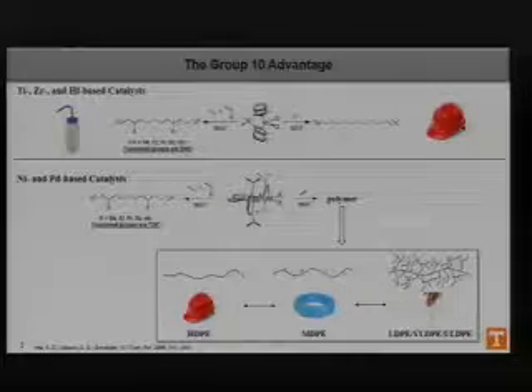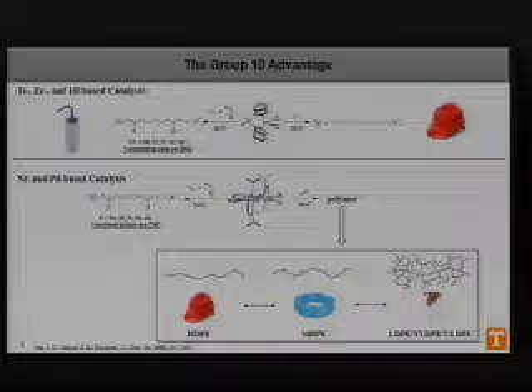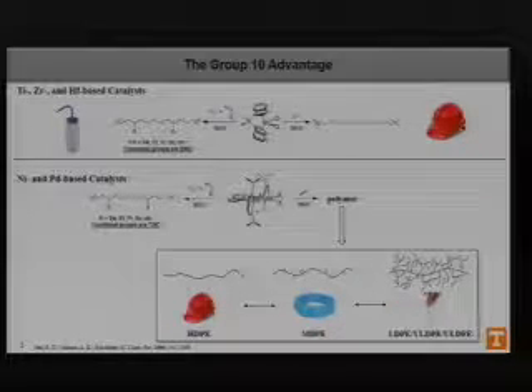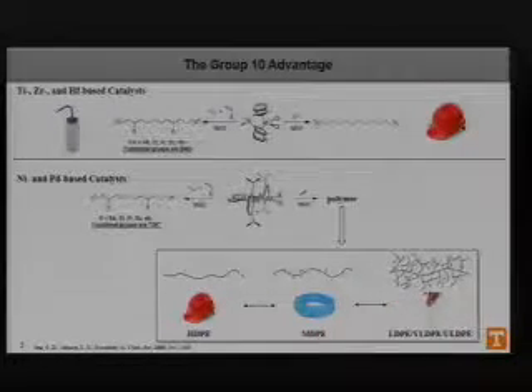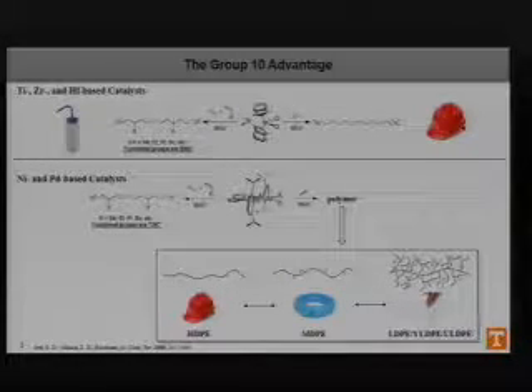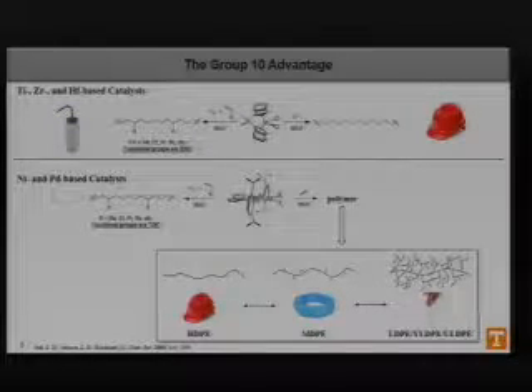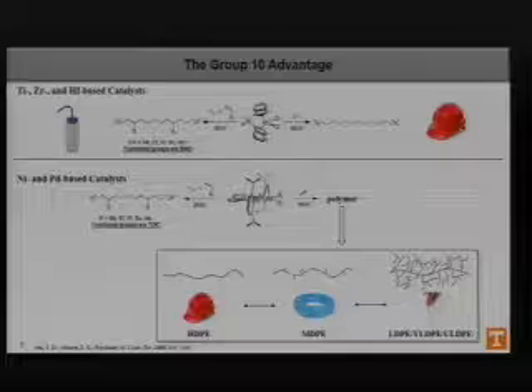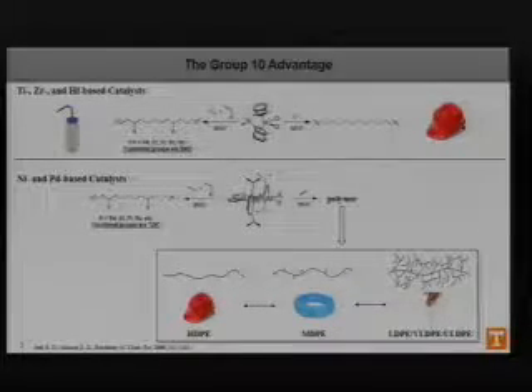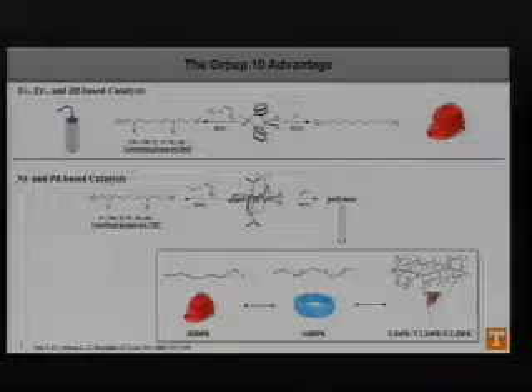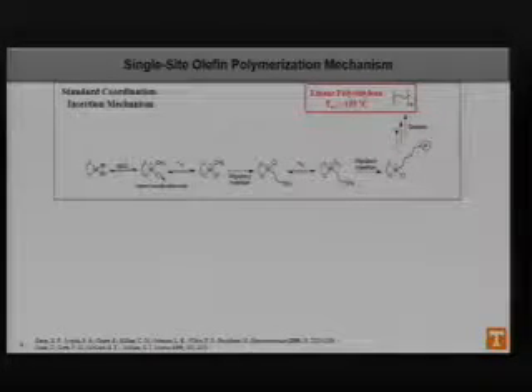before, medium-density polyethylene, which is slightly more flexible but still a pretty rigid material, all the way down to low density, very low, and then ultra low density, which is something similar to the adhesive type structure that I have shown. Now, the only difference in terms of the architectures here is the increasing amount of branching that exists between each one of them. Now, to understand how these group 10 metals can actually create all these different materials using only the single feedstock, we have to actually look at the polymerization mechanism.